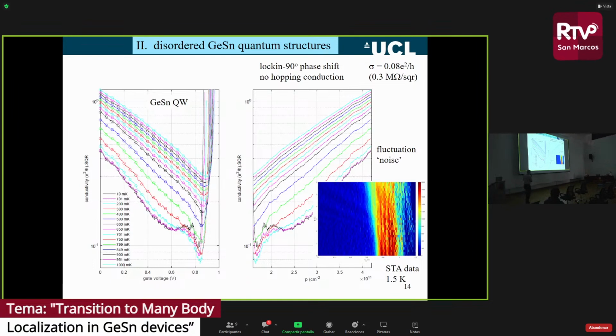I've also plotted the same data now as a function of carrier density. We see this very, very clear transition at this point. For this particular data, we totally lost the conductance, whether we've lost the contacts or the system just, well, it would be nice if the system collapsed into a many-body localized state, but I don't think it does. Interestingly enough, what we also see in this data when we apply a magnetic field, so this is what I'm plotting on this false color plot now, is magnetic field as a function of gate voltage. And you can see when you plot the data in this fashion, you can still see the Landau level structure coming out of there, even though we're deep in this localized regime.